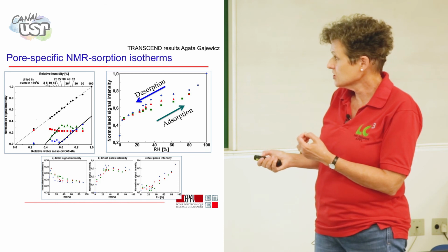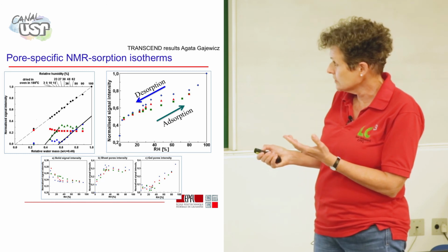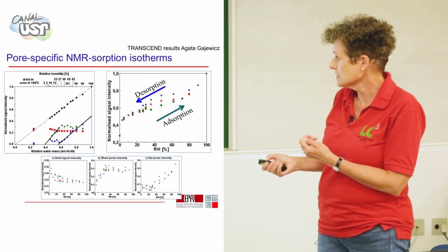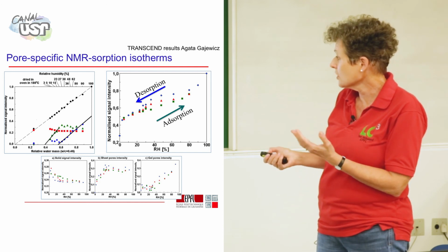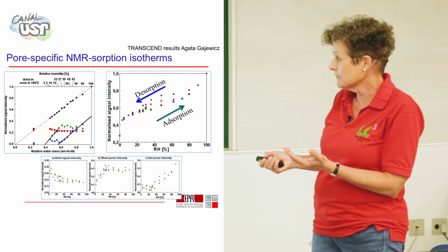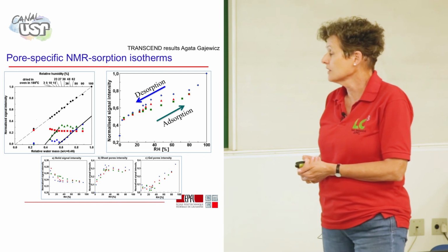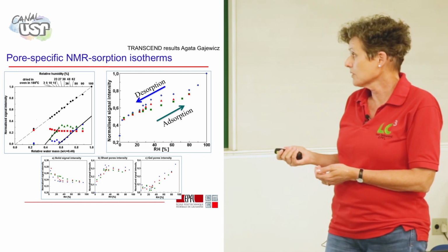And this is the gel water here. So the gel water progressively empties and is empty at about 30–40% relative humidity. Now the capillary pores are on this because right almost at the beginning of the experiment, when you've hardly gone below 100, you're still in the 90s, then the capillary pores appear not to contain any water.